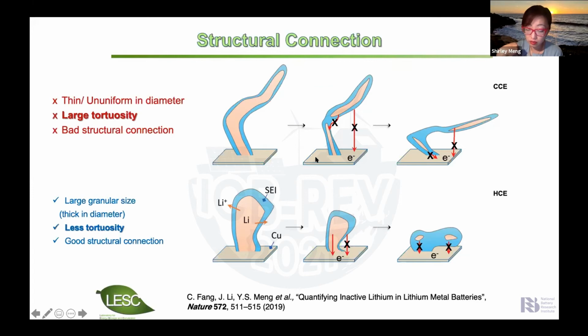But when you discharge your battery, the lithium has to go back to the cathode. If you have this kind of morphology, remember the blue, the SEI contains lithium carbonate, lithium oxide, lithium fluoride. It's very insulating. So if you have an imperfection, then some of these lithium on this part will be totally blocked from the electrical pathway. So in the electrochemical system, even if this is metallic lithium, if they don't have access to the electron pathway, this lithium will be what we call the dead lithium. They will be electrochemically inactive. So the hypothesis is we believe that the SEI is mostly similar, but the microstructure causes a very big difference in the Coulombic efficiency for the battery.